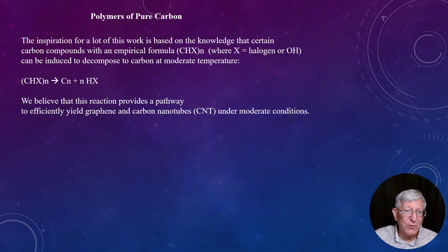And so, how do I fit into this as an organic chemist? Well, it turns out when I got to looking at the technology that was being used to make these carbon compounds, I found that methane is the material that people are using to make carbon nanotubes. That's not what an organic chemist would start thinking about. And it became apparent to me that maybe there's a much better way to do this. Maybe we don't have to have 10,000 degree temperature and all this other stuff and the limitations which the thermal decomposition of methane requires to make carbon nanotubes.